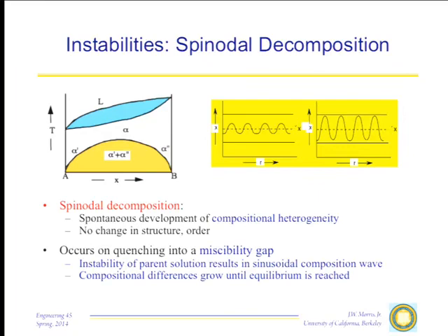The first graduate out of my research group went to Bell Labs from here and invented something called Chromindur, which was a very, very good magnet material that has been used in every telephone headset of a certain generic type for the last 40 years. What he did in that, he wanted to create a material that had very small islands of ferromagnetic material embedded in a non-magnetic matrix. So he arranged a situation in which he got a spinodal decomposition.